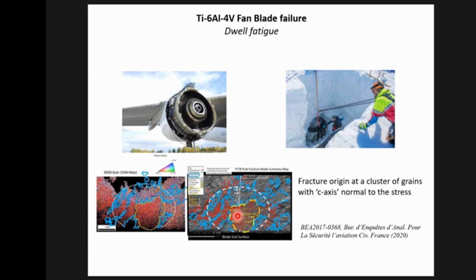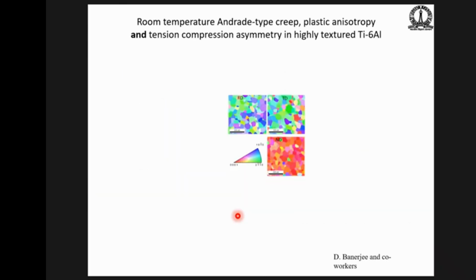Now, we got into this because somebody paid us money to get into it. But then we realized that this is a very complicated problem. We backed off to look at a simple case of a highly textured titanium alloy, which is shown here, where you have a very strong, it's a rolled plate. So the normal of the rolled plate is very strongly 0001, which means in the plane of the plate, you're looking at something which is largely in the basal plane.